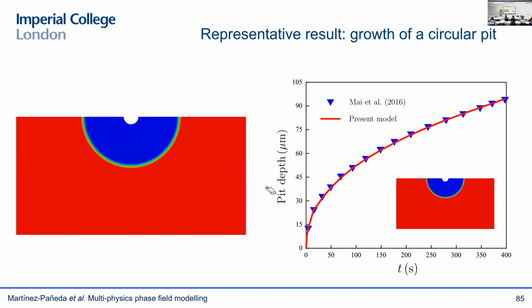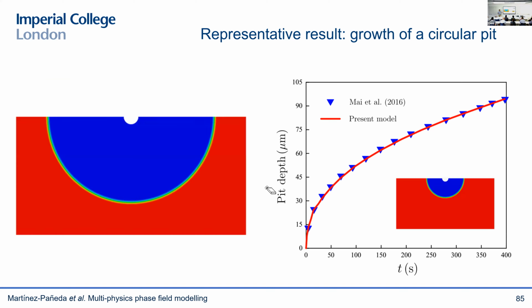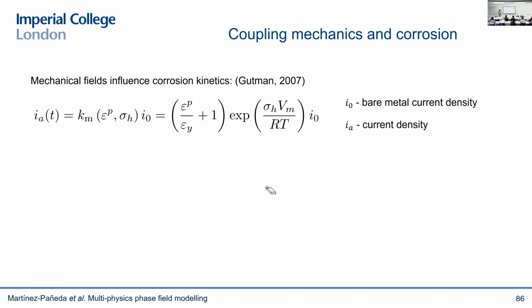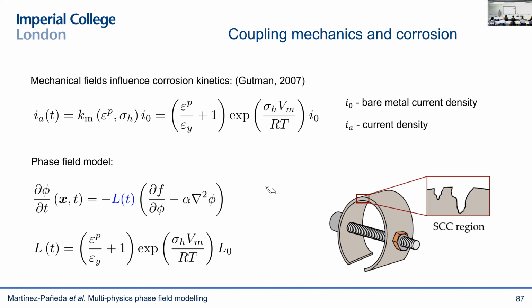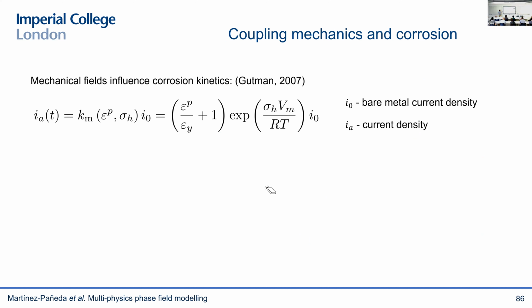We can also compare with other computational studies, and you can see here, this is just a void growing uniformly. There's no mechanical load here. But what I think is more interesting is incorporating these mechanical effects that can play a big role. And there's essentially two big mechanical effects here. One is that we know from a long time that mechanical fields enhance corrosion kinetics. So this is the corrosion current density, and you can see that it's enhanced by the plastic strains and the hydrostatic stresses.